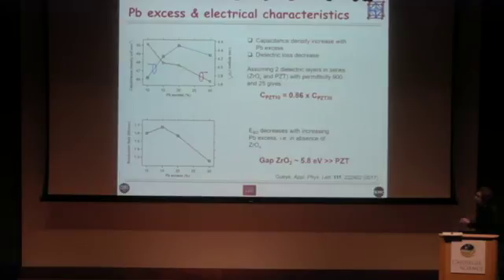Other electrical results on these capacitors now as a function of the lead excess. First of all, the capacitance density, if you use surface area, actually increases with increasing lead excess. So this is quite important. It's 10%. It's quite significant. The loss tangent decreases, which is good as well if you want some high-performance devices with lower power consumption. But unfortunately, the breakdown field actually decreases with increasing lead excess. And the decrease is quite important. It goes from 1.6 to 1.3.